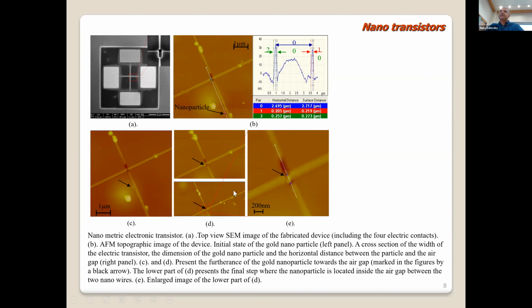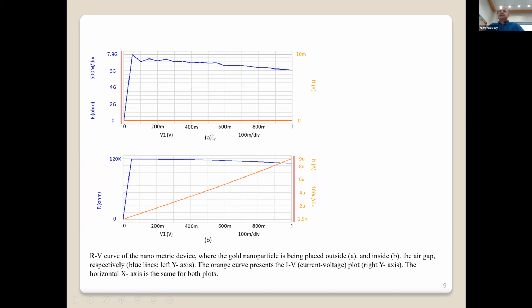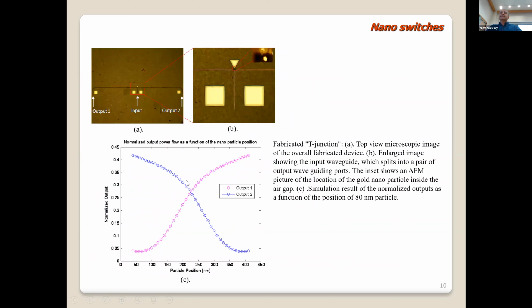Here you can see some experimental results. You can see, for instance, the blue line, which is the measurement of the resistivity between the source and the drain. This is the resistivity when the nanoparticle is shifted away from the source and the drain. The resistivity is high, about 8 gigaohm. And when it is shifted to be positioned between the source and the drain, the resistivity is significantly lower, 120 kilo ohm. So this is a nanometric transistor.